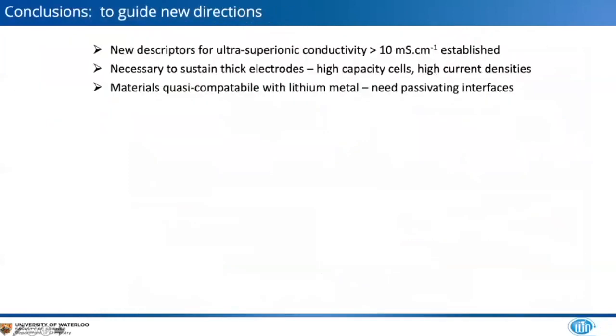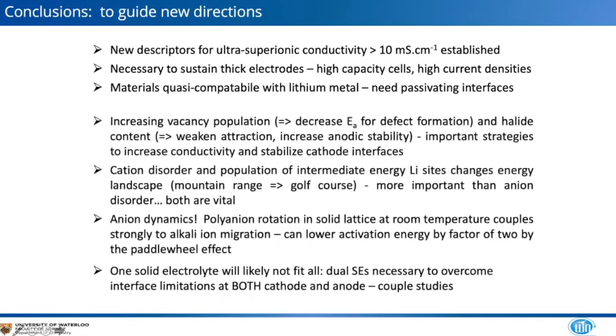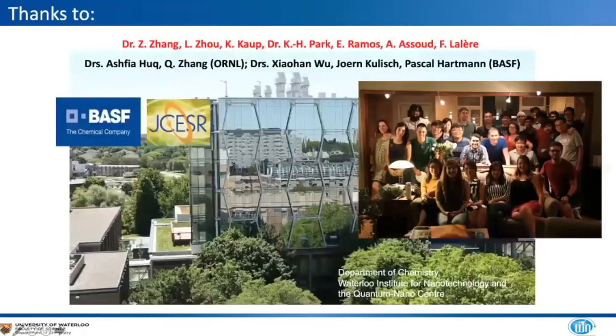So with that, and 2 minutes left to go in my 35 minutes, I'll just briefly summarize by saying that we have some new descriptors established. I would remind the audience of the need for high ionic conductivity to obtain high current densities. The issue with lithium metal does need to be addressed. And I've highlighted all of these points: increasing the vacancy population, strategies to increase conductivity and stabilize interfaces, for example with halide materials, controlling cation disorder and anion disorder, the importance of anion dynamics, and polyanion rotation, which can enhance the conductivity by a factor of 2. And one solid electrolyte is unlikely to overcome all of these challenges, and so bifunctional or dual electrolytes are probably necessary.